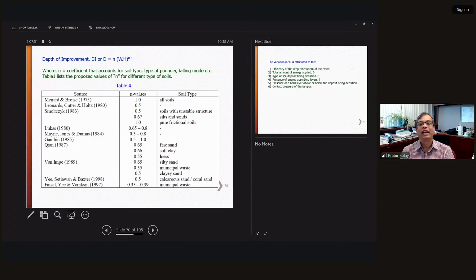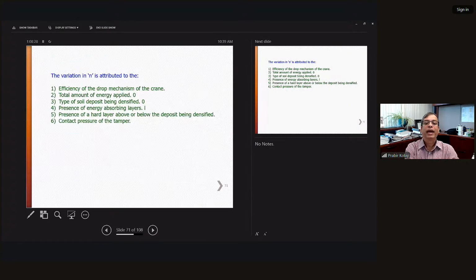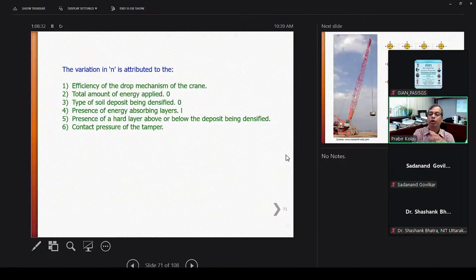As I mentioned, D, the depth of improvement or densification, is equal to N times the square root of W times H, where N is the coefficient that accounts for soil type, pounder, falling mode, all these things. Different people have given different N values for different types of soil, so we need to check that. This will give you a guideline for how much depth of improvement you can get, and you can use these N values to calculate it. The variation of N is attributed to the efficiency of the drop-off mechanism of the crane, the total energy applied, the type of deposit being densified, and the presence of an energy absorbing layer. A lot of things you need to check, including the contact pressure of the tamper.